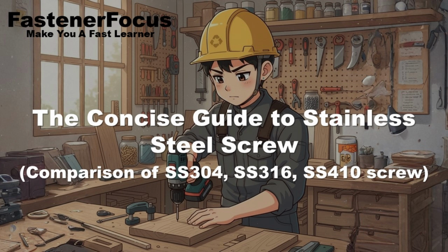Precisely. This failure mode can be highly localized and destructive. We often see it where a beautiful stainless steel screw is perfectly fine, but the galvanized washer or the aluminum substrate surrounding it is dissolving into white or red powder. This is why material compatibility is just as important as environmental resistance. You must either use materials close in the galvanic series or, more commonly, introduce a complete non-conductive barrier.